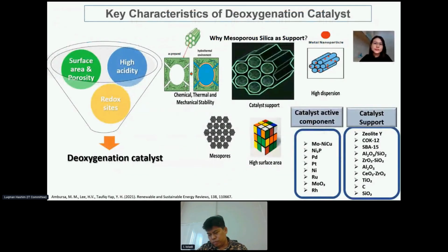In order to enhance the efficiency of the HDO process with high yields and high selectivity of products, one of the important criteria that our group focuses on is the deoxygenation catalyst. It has been reported that the key characteristics of a deoxygenation catalyst should consist of, first, large surface area and porosity, which help to enhance the accessibility of the feedstock to the catalyst during the reactions. Secondly, high acidity of the catalyst, which can favor the desired reaction pathways that I mentioned in the previous slide. And thirdly, the presence of redox sites that promote the hydrogenation functionalities of the feedstock.